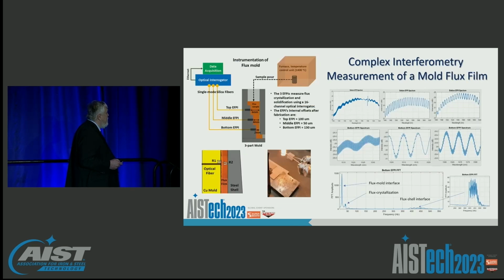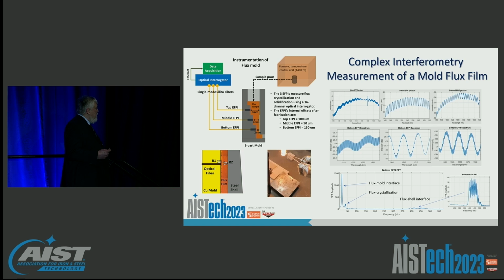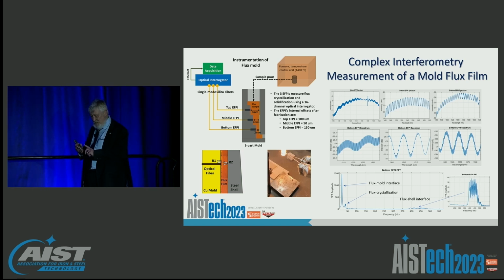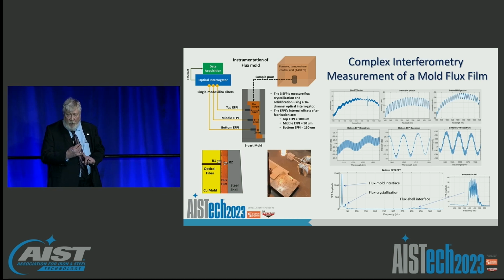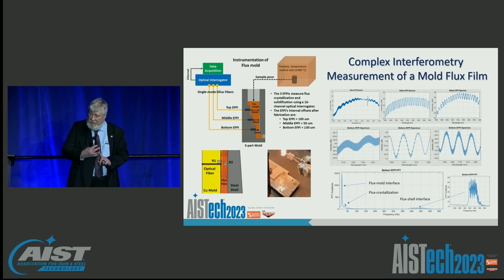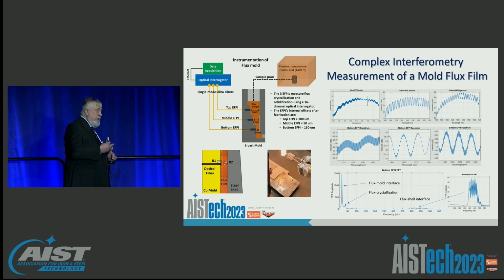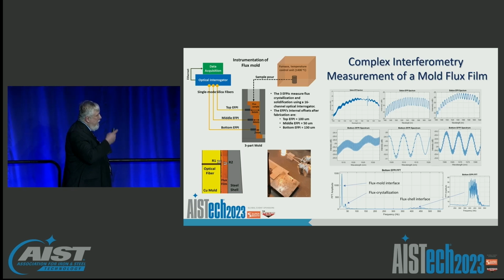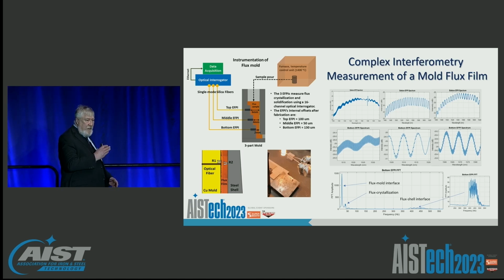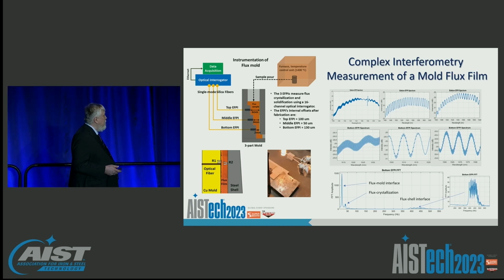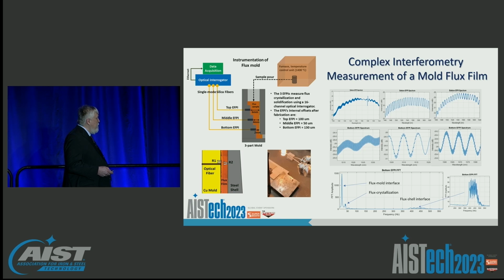It's actually pretty exciting. One of the things that we're looking at right now is, can we put one of these in a mold and actually get information about the flux and the flux crystallization directly? And if we use these interferometers, the reflection off of reflecting surfaces can give us a lot of information. What's the interfacial gap between the surface of the flux layer and the mold? Is there a presence of a crystalline layer, and where is it forming? And potentially even reflections related to the flux contact with the shell surface itself. So we can monitor all three of those with a single interferometer by actually taking the interference patterns and in the frequency domain identify those key peaks that are related to that interferometry pattern. And so we've been able to detect things like flux crystallization. This is a small, essentially, cell experiment that we've done that demonstrated we can see these things. Actually, I think it's showing there.